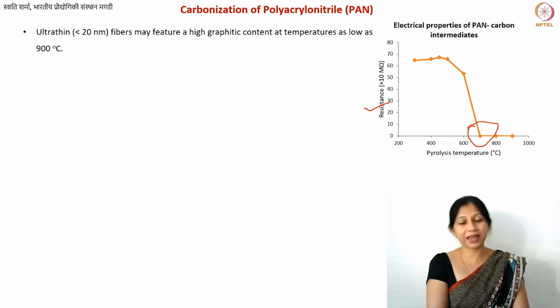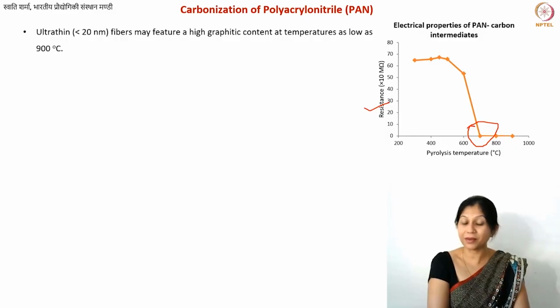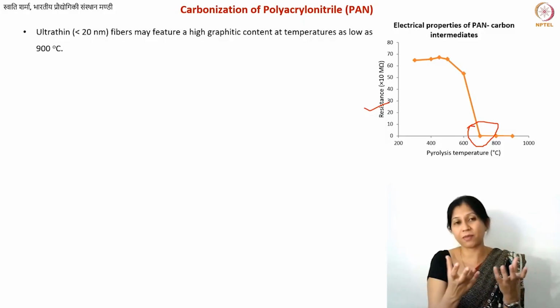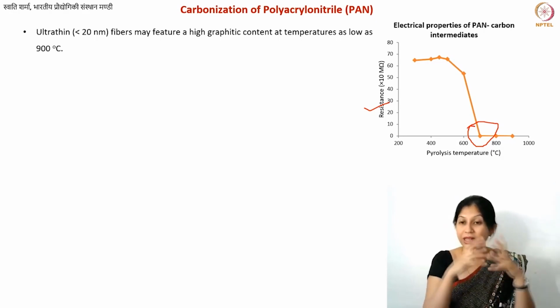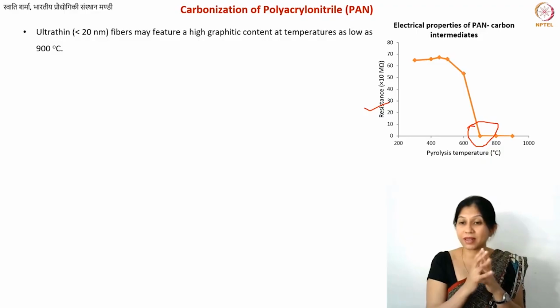Number one, in the case of fibers, as I said, the defects can anneal out relatively easily. So you cannot always say that you are never going to get graphite out of it. Although under normal circumstances that does not happen, because there will be some curved carbons that are formed. There may be some fullerene-like structures, although in the case of fibers it is less likely, especially when you have fibers as thin as 20 nanometers, then it is possible that these defects will anneal out. However, there will be some curved carbon structures. So this is more of a non-graphitizing type carbon, and that is why you should not get graphite out of it.